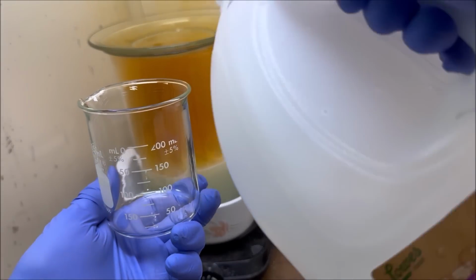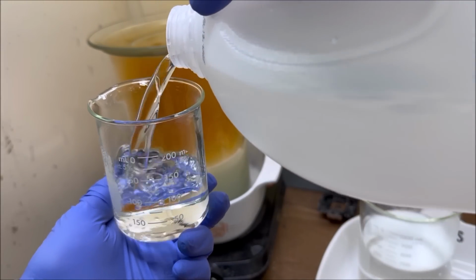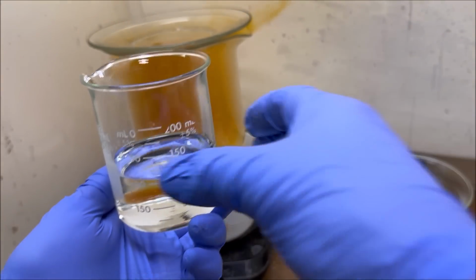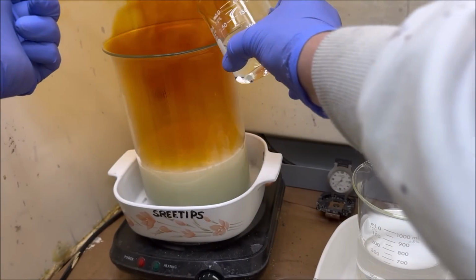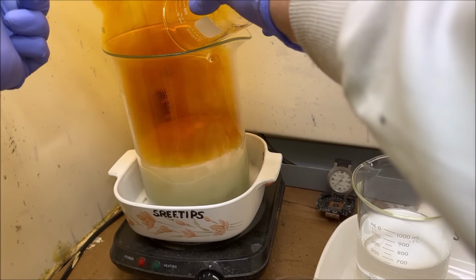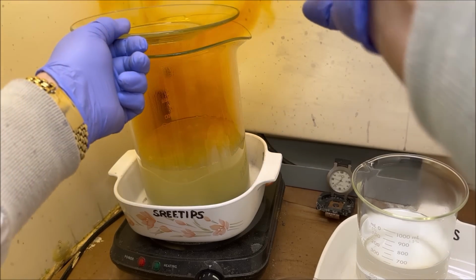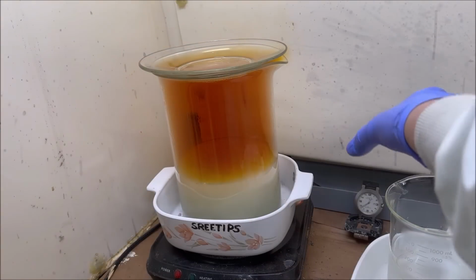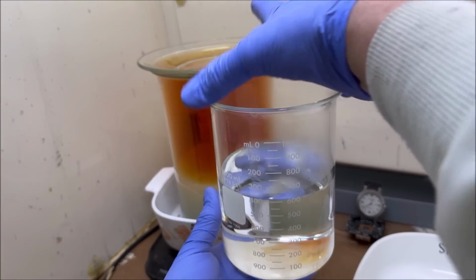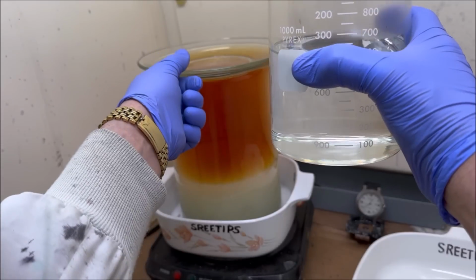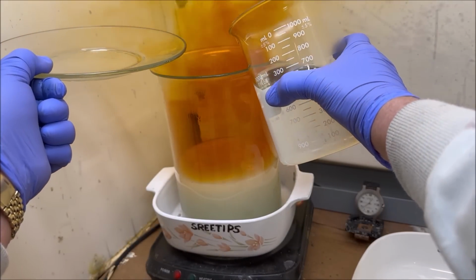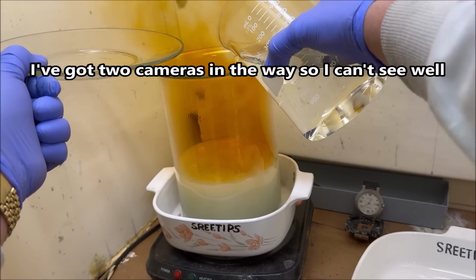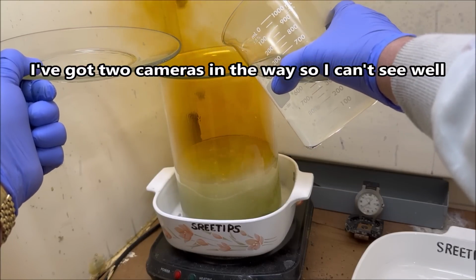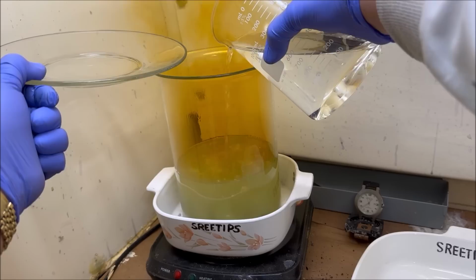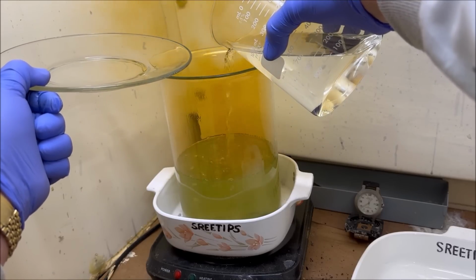I'm going to add a little bit more distilled water just to make sure that we've got plenty of distilled water as a medium for the silver to dissolve into. Let's pour in a little bit more nitric acid. The trick is to get this all in here safely without creating a boil over. And once we get all this nitric in there, boy oh boy, we should be able to dissolve all this silver.